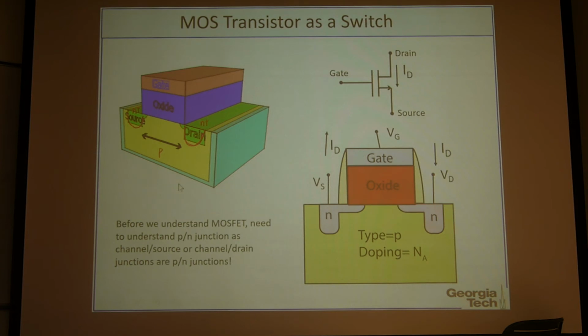So that means in the fabrication process, you are going to first dope the substrate with some P-type dopant, for example, boron. And then you need to define two regions. One is called source, one is called drain. And in those two regions, locally, you are going to dope with N-type doping, for example arsenic, only to those two regions. And then, between the source and drain, you are going to grow the oxide. And on top of the oxide, you will have the metal, like the gate.